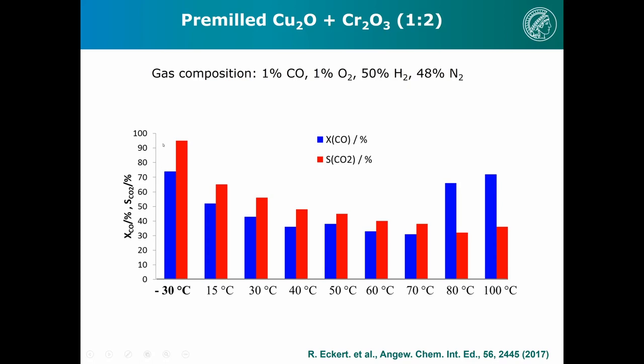Strange. Normally, activation energy tells you you have to increase temperature for conversion to go up. And at the same time, the selectivity also goes up, reaching almost 100% at minus 30 centigrade. So we have here a reaction with a negative apparent activation energy, which is not unheard of in catalysis. It's often the competition or the interplay between adsorption and surface reaction. Here, we think we have the interplay between surface reaction, which has a normal activation energy, and the